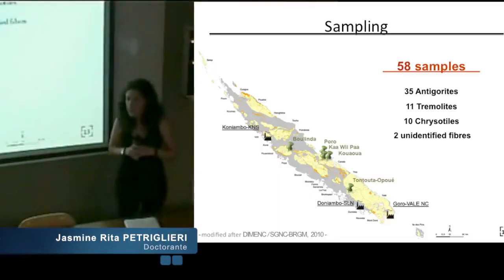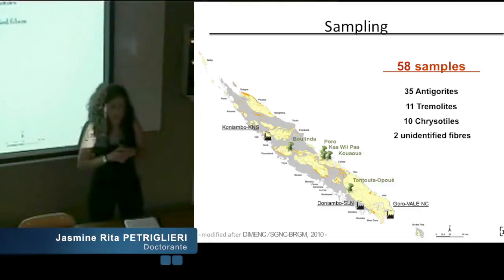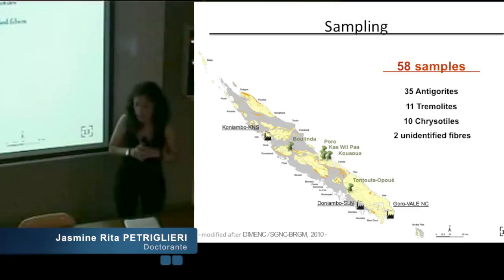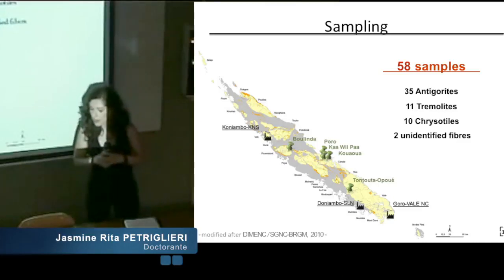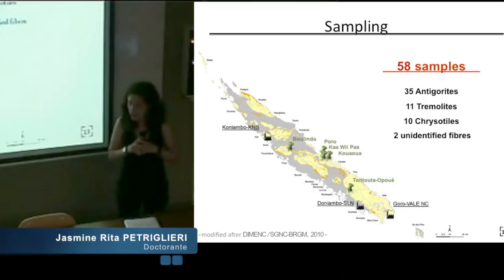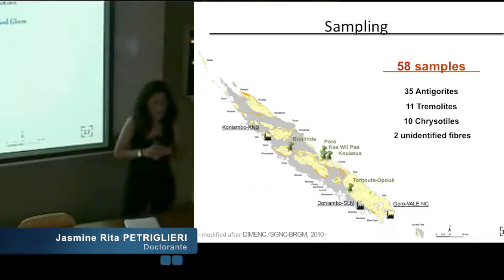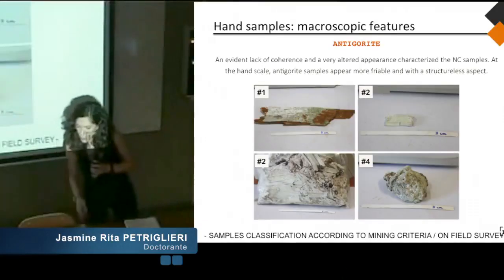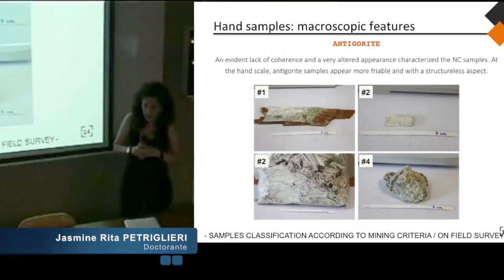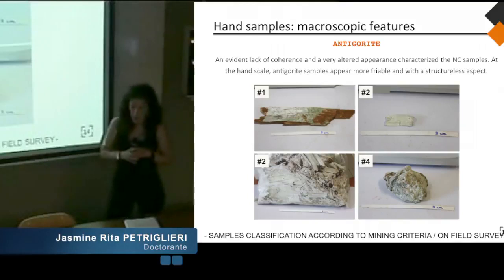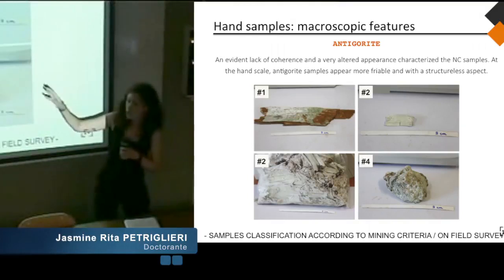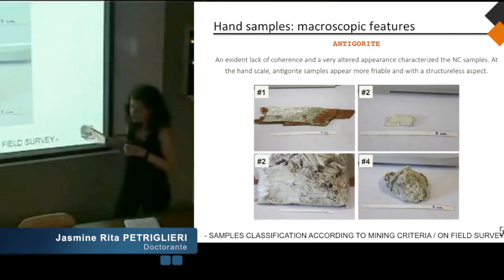Concerning the sampling, 58 samples were collected by geologists of mining companies: 35 antigorites, 11 tremolites, 10 chrysotiles, and 2 not identified fibers. All samples present different degrees of alteration and were collected from the most important geological units of the country. At the outcrop scale, samples of New Caledonia show an evident lack of coherence and a very altered appearance, especially for antigorite, increasing the degree of alteration from 1 to 4.